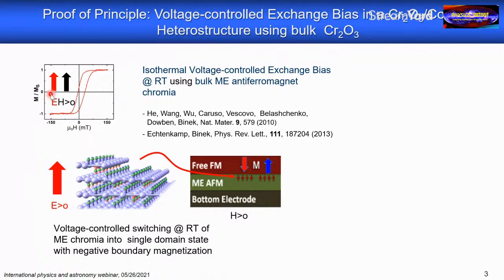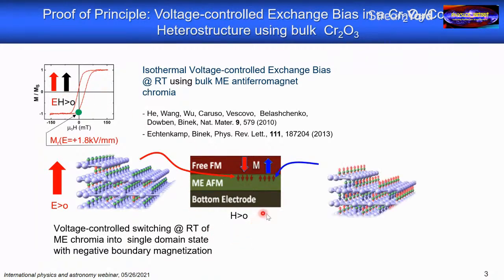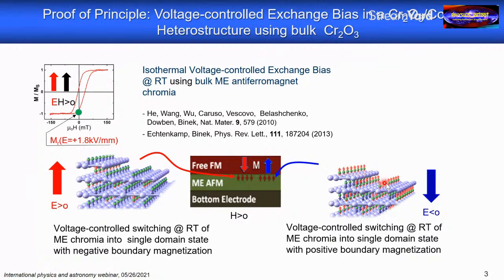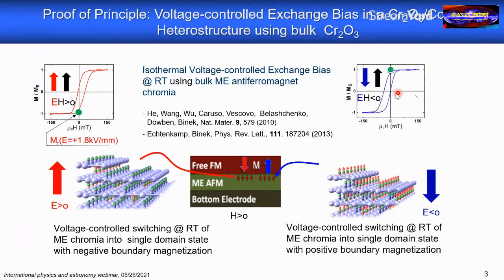So as a matter of fact, what decides whether the hysteresis loop of this ferromagnet goes to the right or the left is the sign of the product of the applied fields. If the product sign is positive, we have a positive shift. If the product sign is negative, we select the different boundary magnetization, and with that we select the different shift to negative fields. So these were the first two proof of principle results, and then we asked, of course,